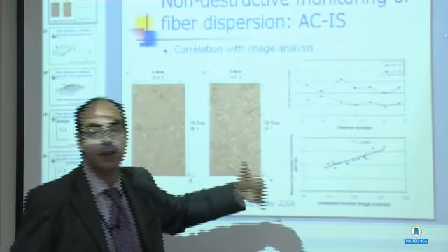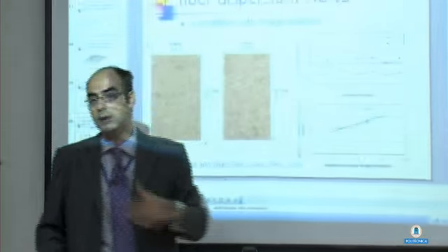This is an orientation parameter, basically a fractional directional conductivity. You weight the conductivity or resistivity in each direction to the sum of the three directions, and you compare with the orientation number, and there seems to be a good correlation, which was a proof of the reliability of the methodology. At least that is how they interpreted it.